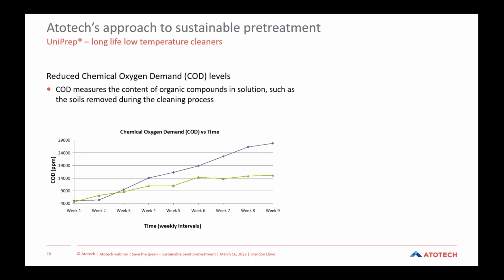So with the UniPrep cleaners, we're also able to reduce the chemical oxygen demand, or the COD levels. And the COD itself is going to measure the organic compounds in solution, that being the soils that are removed during the cleaning process. So you can see in the graph on the bottom of the page here an example of a study that was done of a conventional cleaner system versus a UniPrep long life system, the UniPrep long life system being the green line along the bottom. And here you can see in this study that we're able to reduce the COD by as much as 46% across this nine-week life cycle.